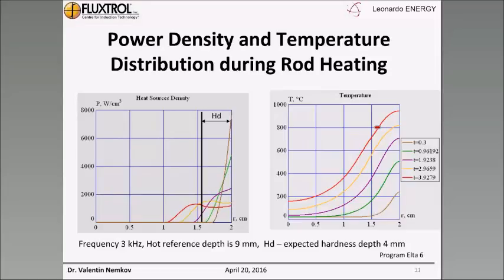centigrade. That's very important: the current temperature distribution in the area of hardening is almost rectangular, and there is no overheating of the surface as it happens in the case of flame heating, for example.